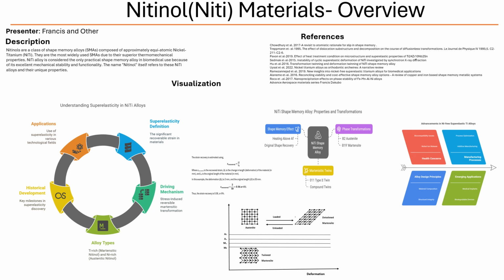While the amount of nickel that's typically released from these devices is usually very low, much lower than what we get from our diet, minimizing that release is still really important, especially for people who are known to be sensitive to nickel. And to make things even more complex, researchers are using computer simulations, like finite element analysis, to try to predict how these NiTi arch wires will behave mechanically under those complicated conditions in the mouth. So it sounds like there's this constant balancing act between trying to take advantage of NiTi's amazing mechanical properties while also making sure it's safe to use in the body.